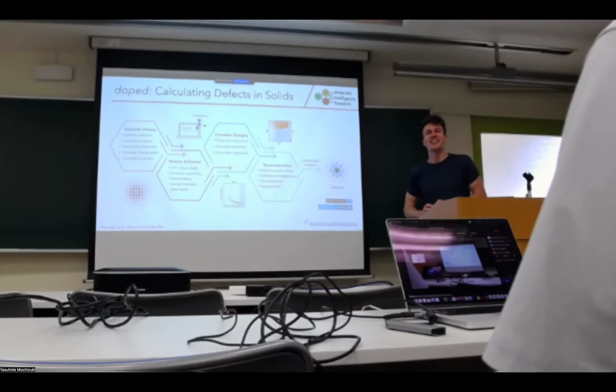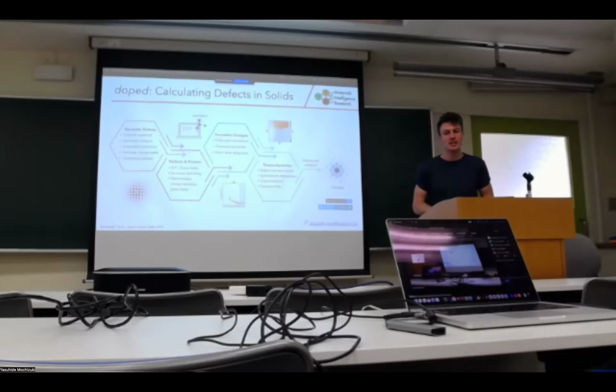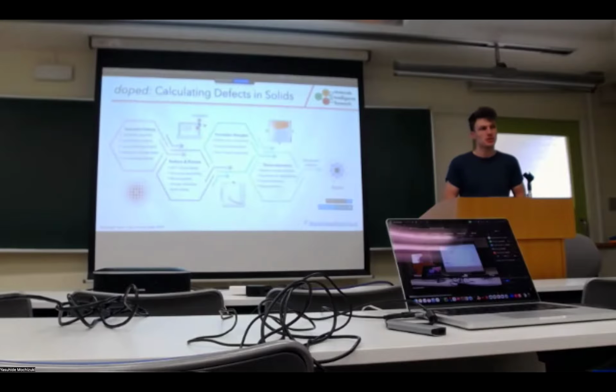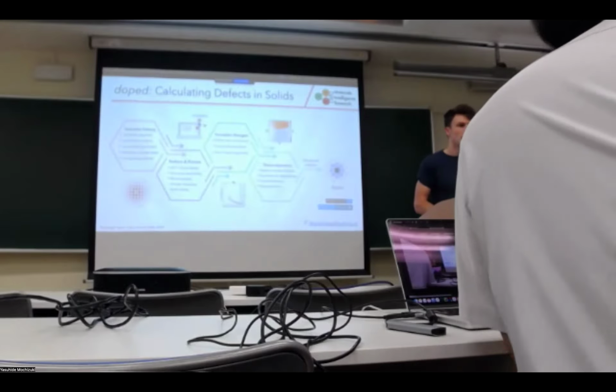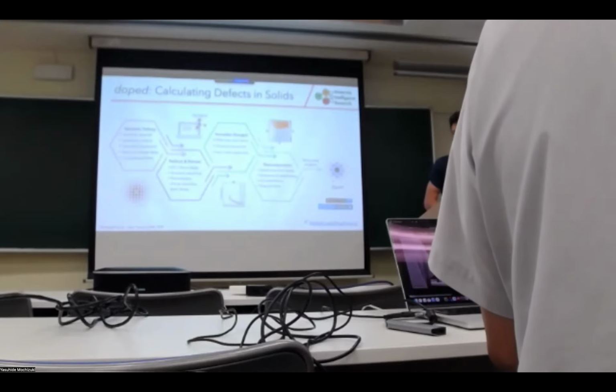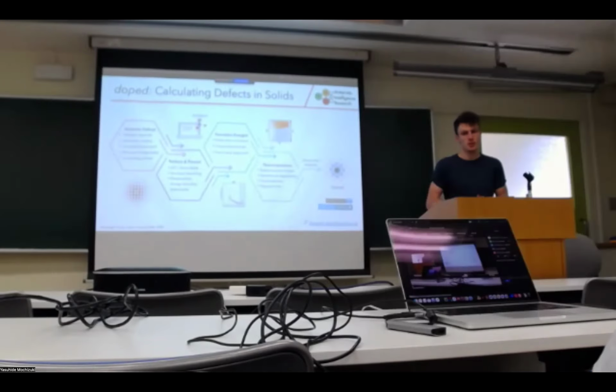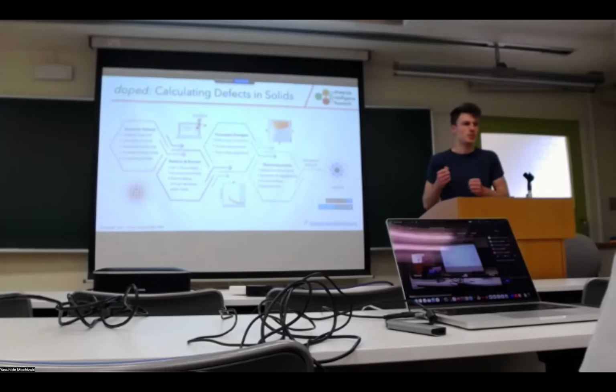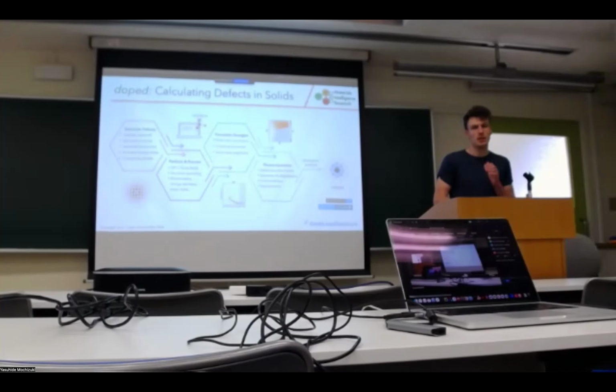I will say that XRD is probably one of the least likely techniques for us to really see this in most cases, because it requires nearly percent-level concentrations of something to see it in XRD. Long-range order, yes. So you need maybe ordered defect structures or an incredibly defective material, maybe some oxides that are super-stoichiometric or substoichiometric. But other things like vibrational spectroscopies are often some of the best ways to see this, particularly if you add in hydrogen and can show that the hydrogen bond would be very different for the different types of defect structures. That's one of the best ways of seeing it directly.